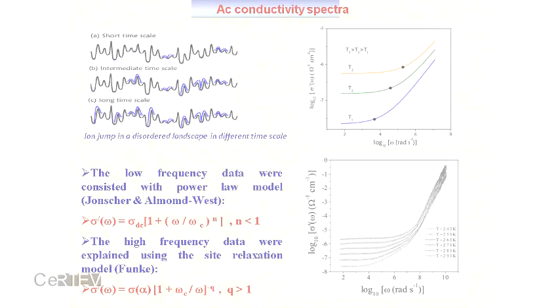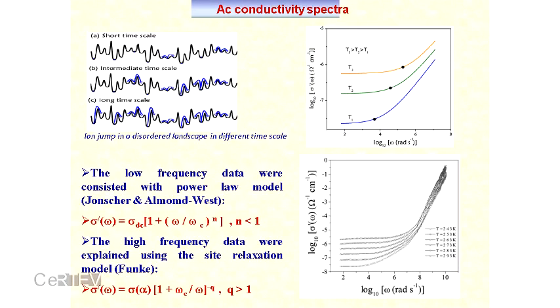Here I have shown the conductivity spectra. You can see a wide frequency range from 10 hertz to about 3 gigahertz. There is a change in the slope after a particular frequency, and this change in slope is not so high, but after another particular frequency the change in slope is very high, a drastic change. Here there is no slope; then the slope starts, dispersion starts, and the dispersion is small, and as the frequency becomes very high, the dispersion is very high. So these two regions can be separated and described by two empirical laws.